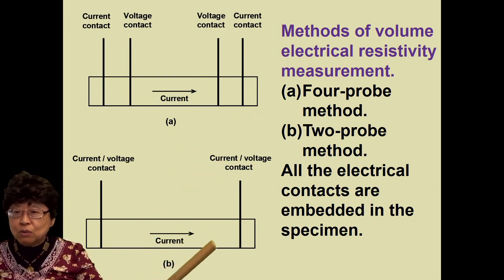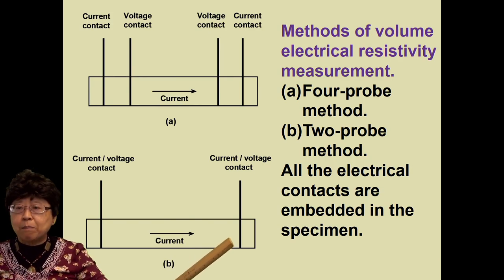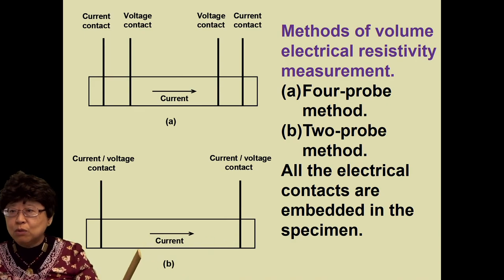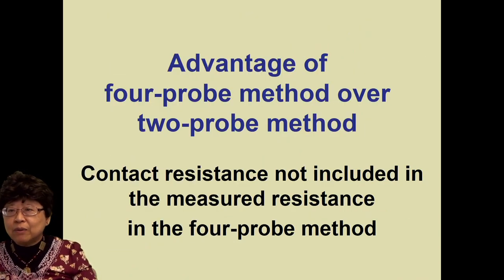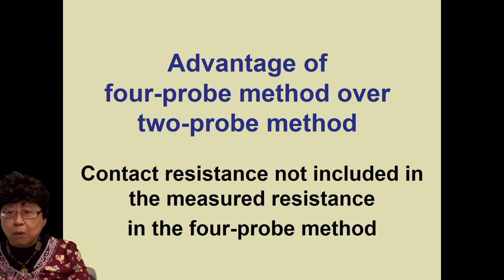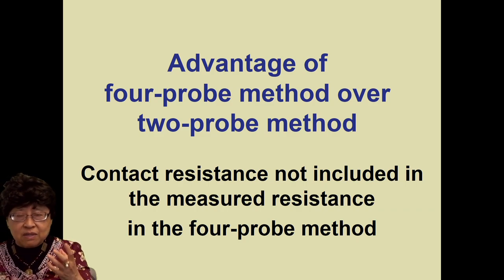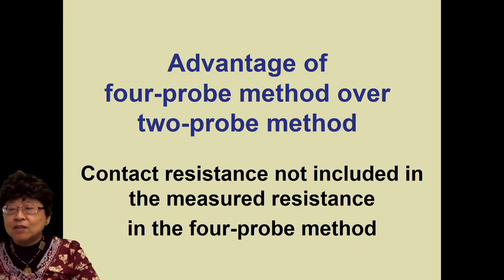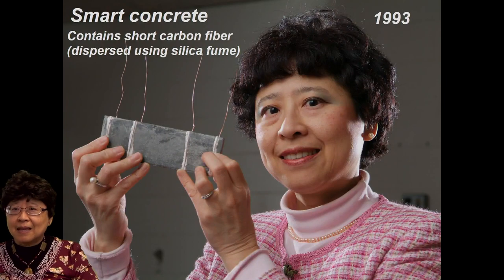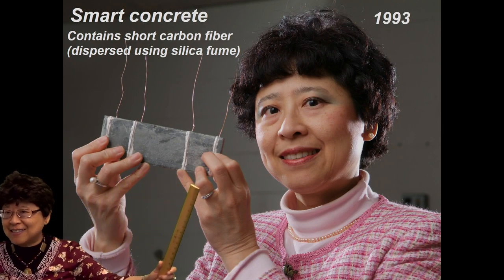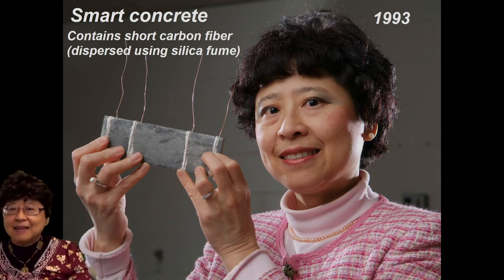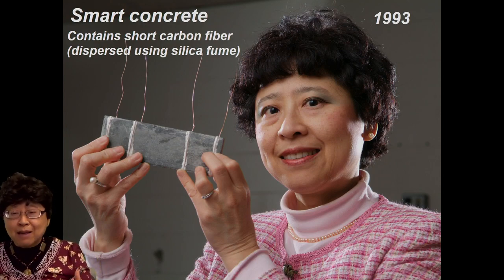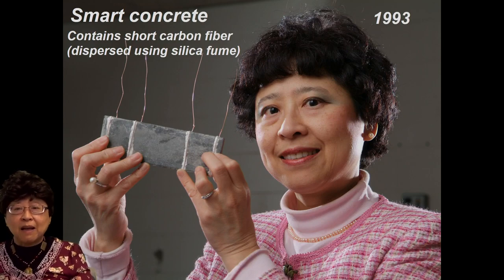However, if you have only two electrical contacts, each contact is used for both current and voltage, and we call that two-probe method. Okay. In general, the four-probe method is much superior to the two-probe method because the contact resistance, that is the resistance associated with each electrical contact, is not included in the measured resistance in the four-probe method, but is included in the measured resistance in the two-probe method. Okay. And you can see that I have four electrical contacts, right? And that's very important. And so it's not just a matter of developing the concrete. It's also a matter of measuring the concrete in terms of its electrical behavior correctly.